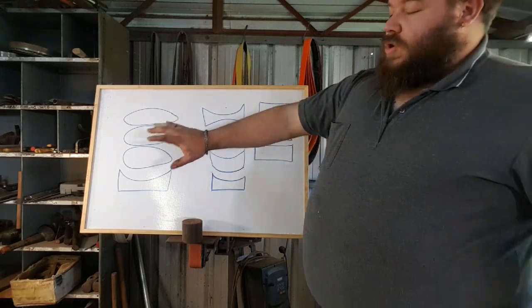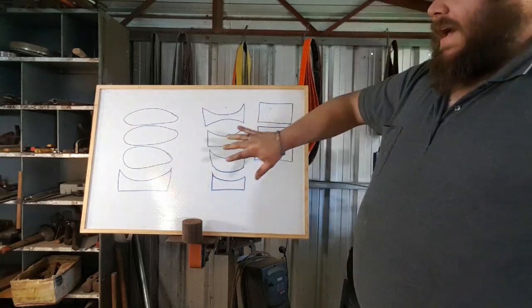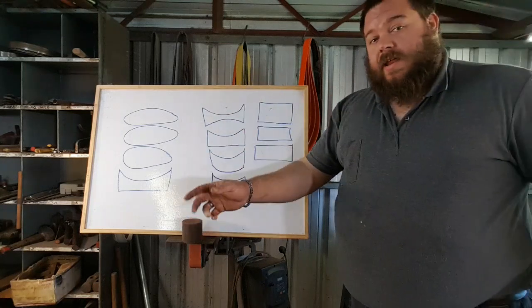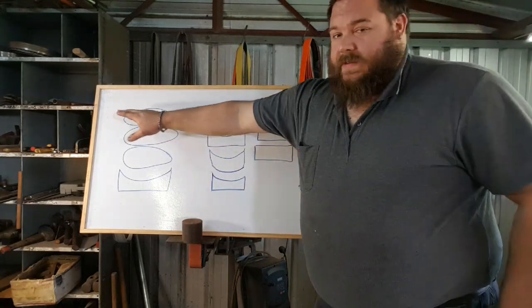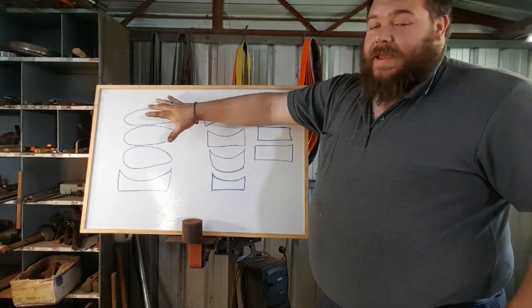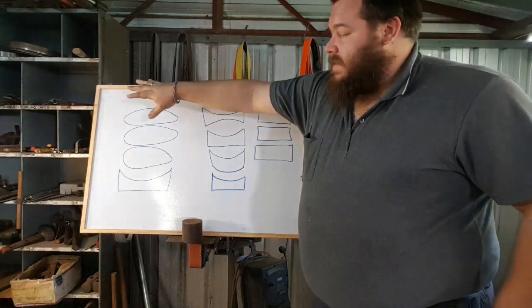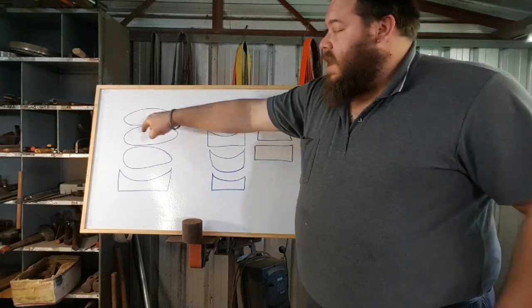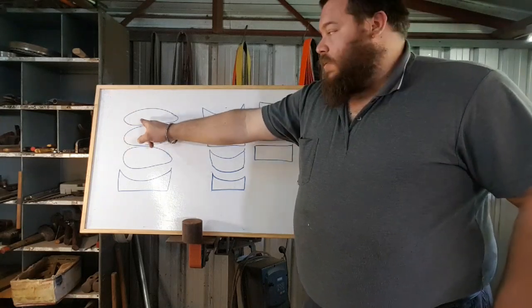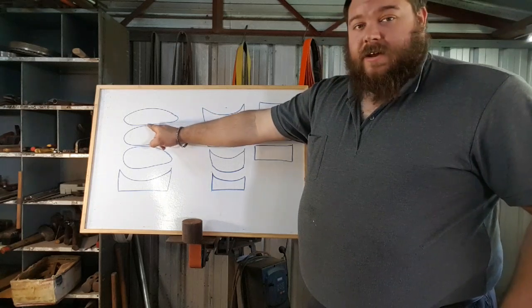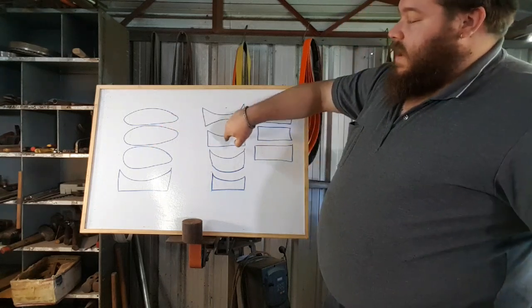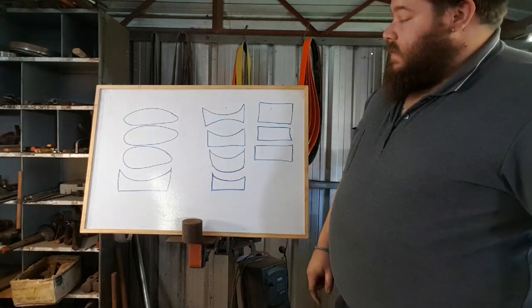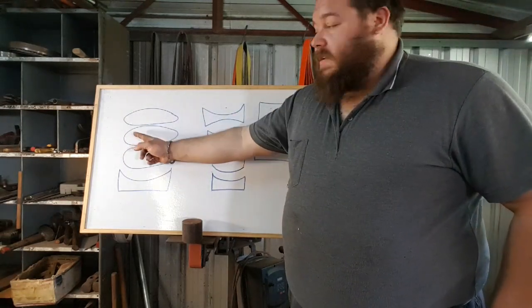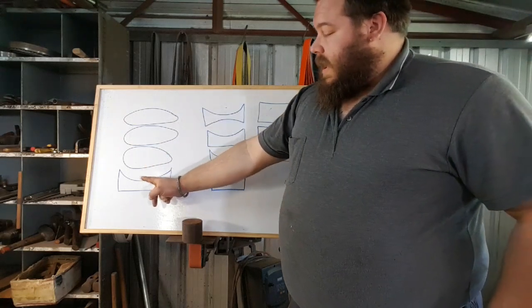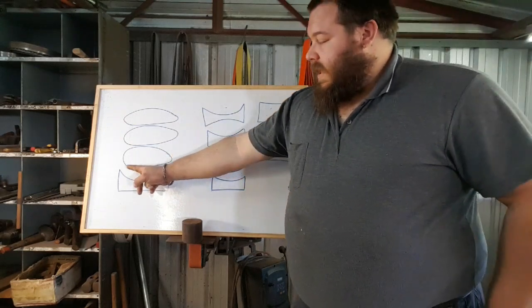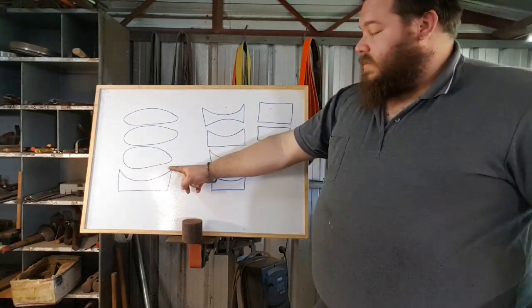So if you're going to use something that's not quite as reliable or flat as my grinder, or say a surface grinder or something like that, then you want to go for this ovular kind of look. Again, it doesn't have to be this bad. You could have flat sides, but if the surfaces themselves are contoured outwards, with the high point being in the center, then these are going to make contact first, which means that all of the material outside of that is going to squirt out. So that's why when you're cleaning and grinding a material, you want to aim for this shape. And again, just to show, that contour is not quite as large as this contour here.